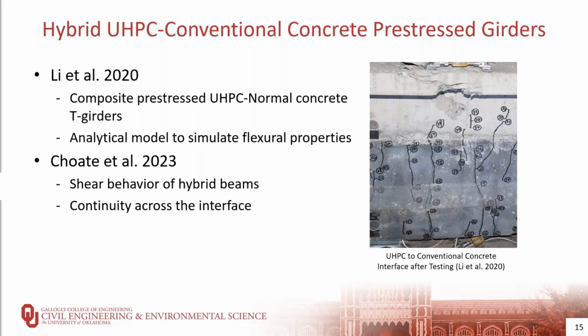As the end region in prestressed girders has been a concern, a different design of hybrid prestressed girders was evaluated by a research study conducted at the University of Oklahoma by Choate. The intent was to use the UHPC at end regions, and the rest of the girder would be just designed with normal concrete. This concept was similar to another research study done at the University of Florida, where they investigated hybrid UHPC SCC bridge girders, evaluated the performance of the UHPC end regions, and tested different interfaces between the SCC and the UHPC.